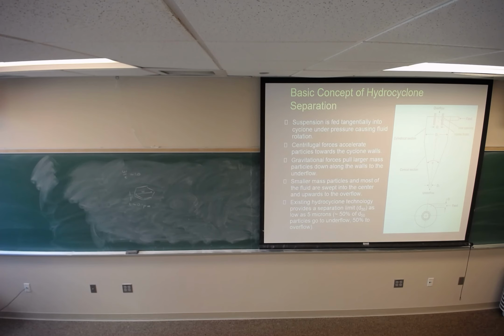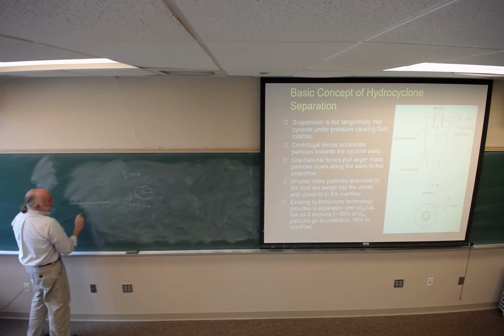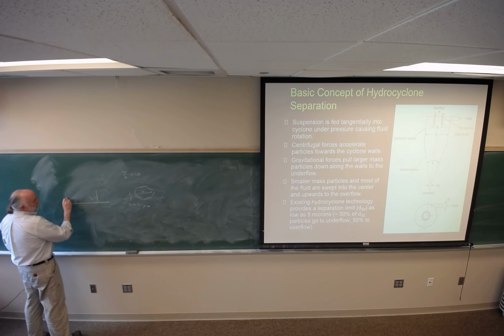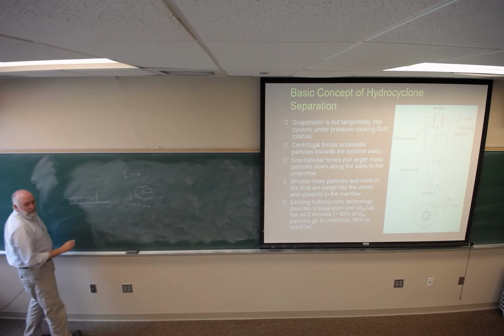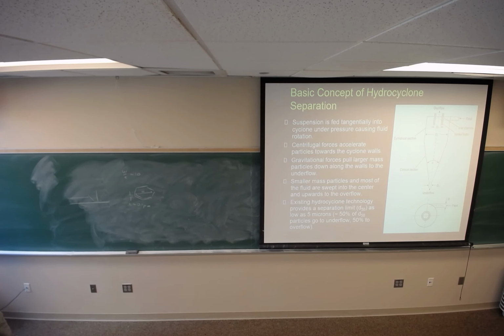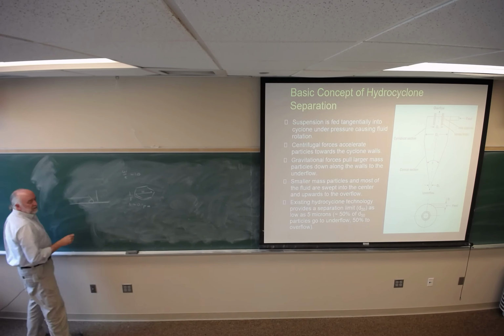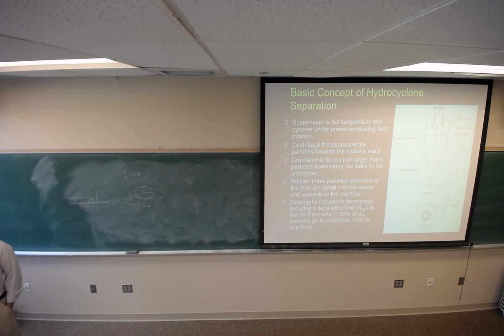So you can take all these clay particles, and you have paper going under a doctor blade with a slurry on it, and the clay particles are aligning under that doctor blade to provide that coating. If you get a quartz particle in here like this, within 2 minutes, if you think about it in terms of the math, you get a quartz particle lodged in the doctor blade. Within 2 minutes, you've made a mile of bad paper. For a coating process, maybe say 3 minutes if you want, but 2.5 minutes. So you're at 1,000 feet per minute, right? In a short period of time, you made a lot of bad paper. So they don't want the quartz. They take the quartz out, and they do it through hydrocycloning.